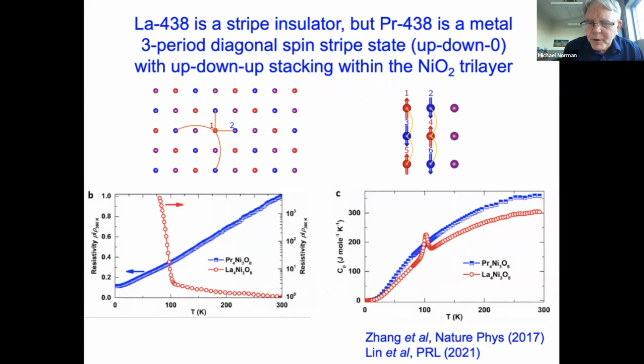And you can see again in lanthanum, you have a pronounced specific heat anomaly, whereas in praseodymium, it's gone. You can see the resistivity on the left. Lanthanum becomes insulating below this stripe transition, whereas praseodymium has a nice cuprate-like behavior, looks quasi-linear in temperature, except at low temperatures, you go over to T squared. Interestingly, the RIXS data actually looks quite similar between the praseodymium and lanthanum. So even though one has long-range spin stripe order and the other one does not, the inelastic magnetic scattering looks very similar.